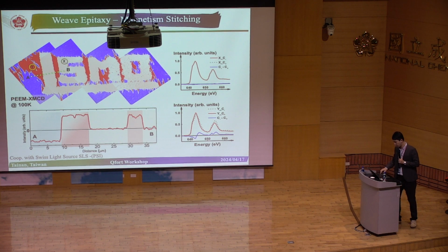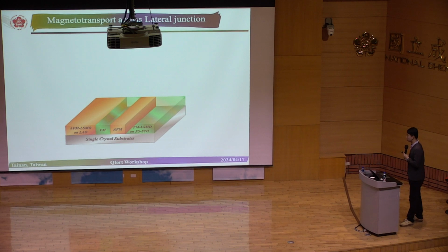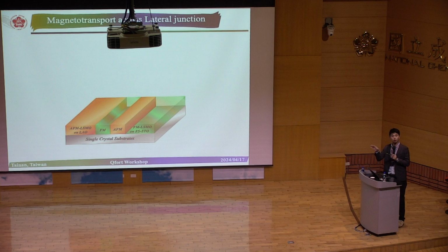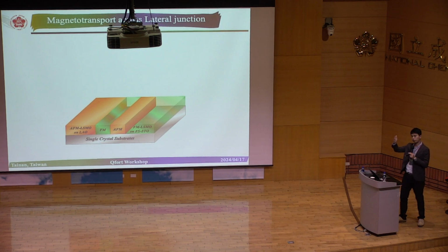Let me guide you through how we can do this using this kind of combination. Here I would like to guide you back to the original stripe architecture, so we can do a nice comparison. To do so, we do everything in the same sample. We have a few areas. We do the transport along this part, which is composed of ferromagnetic unstrained LSMO. We also do the magnetic transport on this part, which is highly strained anti-ferromagnetic LSMO. We also want to do transport along this direction, which is a multi-junction composed of AFM and ferromagnetic orders.